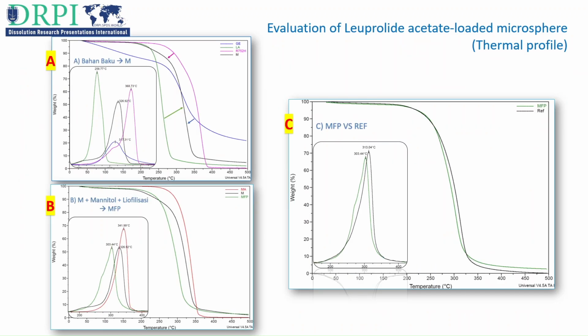These are the TGA thermograms. Figure A shows that encapsulation of raw materials, gelatin and leuprolide acetate, in PLGA resulted in thermal changes with thermal decomposition of microspheres occurring at lower temperatures compared to the pure PLGA. While figure B shows that lyophilization with mannitol as a bulking agent led to thermal decomposition of the final product at lower temperature compared to pre-lyophilized microspheres due to the effect of mannitol. And figure C shows that the final microspheres had thermal characteristics close to the reference product, with decomposition occurring at 303 degrees Celsius, about 10 degrees Celsius lower than the reference.